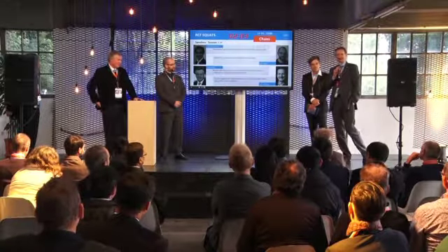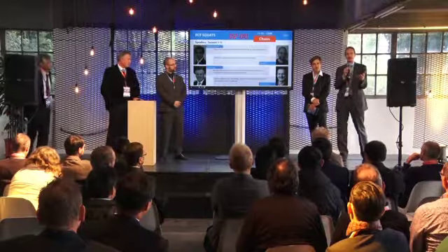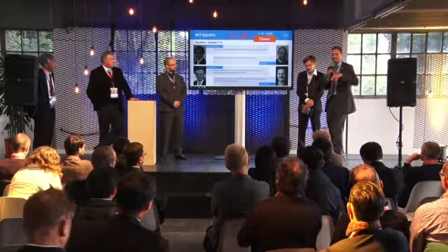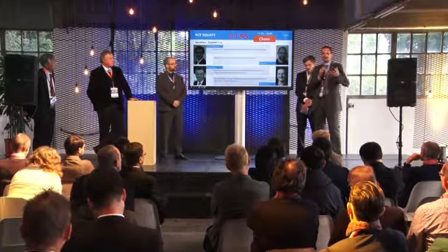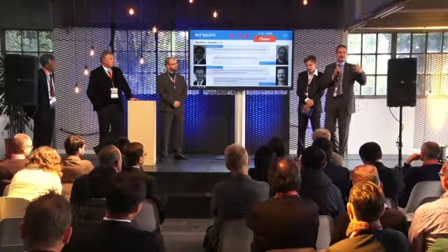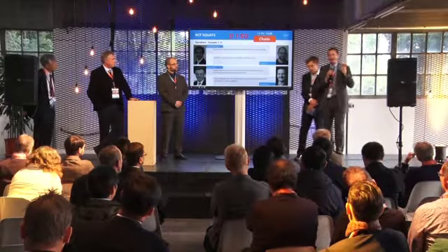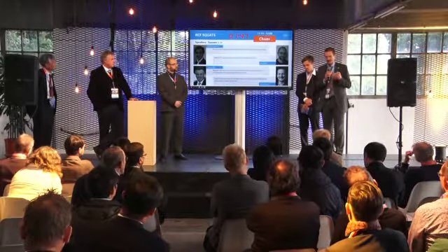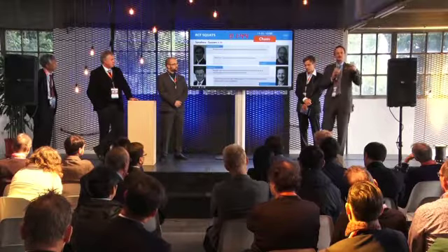So this question, it's not the first time that it comes out about heat-treated rails. Are they more prone to squats or not? To be fair, I'm coming from the rail production side, so I've worked a lot on this topic in my past. I would say the wear behavior of the system is very important. A heat-treated rail is supposed to have low wear. So whatever you do with such a rail, you need to be aware of this and perhaps adjust the profile slightly differently in the beginning so that you can adapt to this.